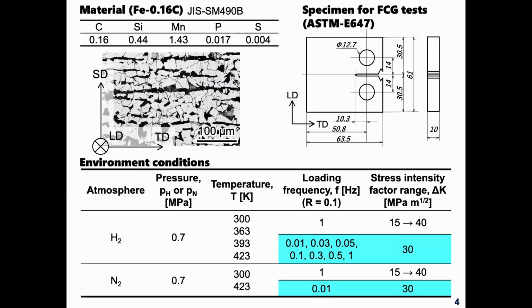The material tested in this study was low carbon steel with 0.16% carbon, which had a typical ferrite-pearlite microstructure. We performed several fatigue crack growth tests using CT specimens in nitrogen gas and hydrogen gas with a pressure of 0.7 megapascals. This presentation will show you a part of the experimental results acquired by delta K constant tests at 30 megapascal square root meters, changing the loading frequency from 0.01 hertz to 1 hertz for various temperatures from room temperature to 423 Kelvin, 150 degrees C.